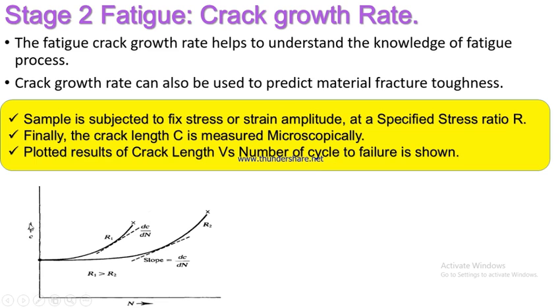So diagrammatically, this is what we are talking about. When you pick a particular sample of material, you subject it to a fixed stress over a long period of time, and the stress will cause the crack in the material to grow. Once you measure the length of the growth, which we denote as C, over the number of cycles the material was subjected to before failure, we plot them together and get a profile like this. The differentiation of this curve, the slope of the curve, is called the crack growth rate.